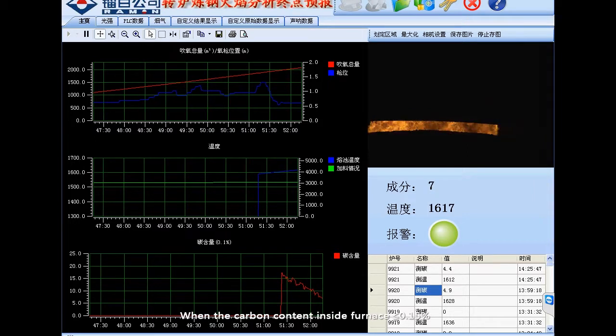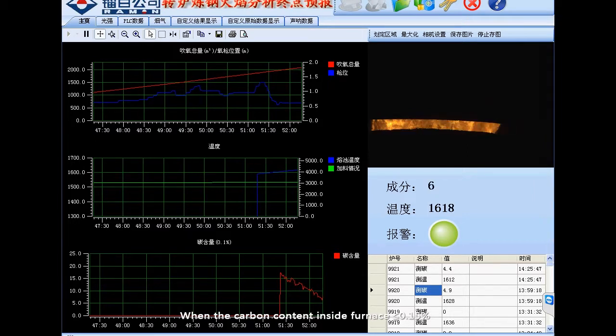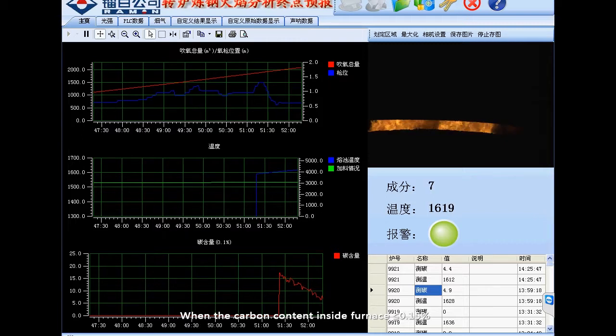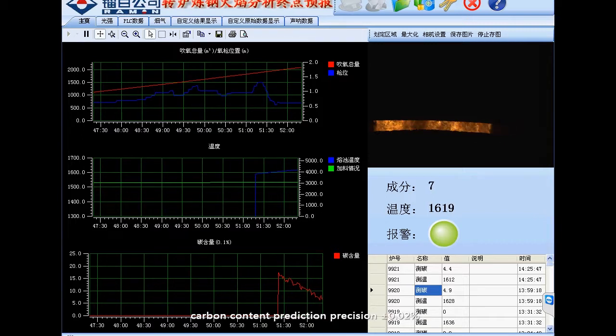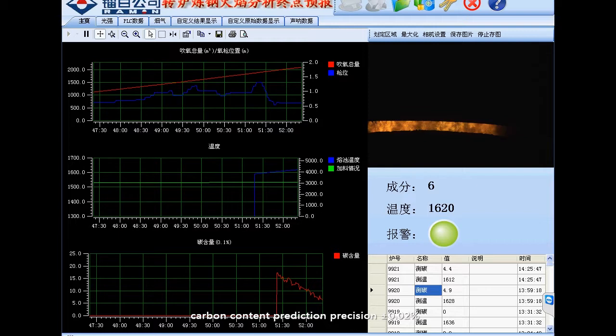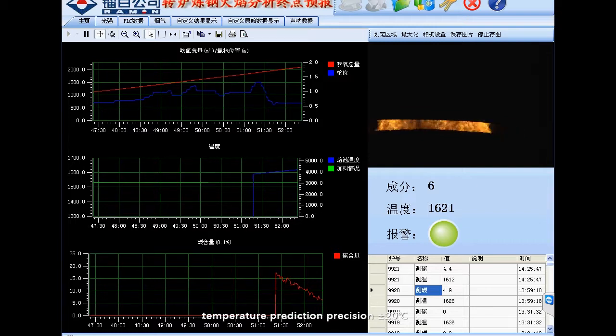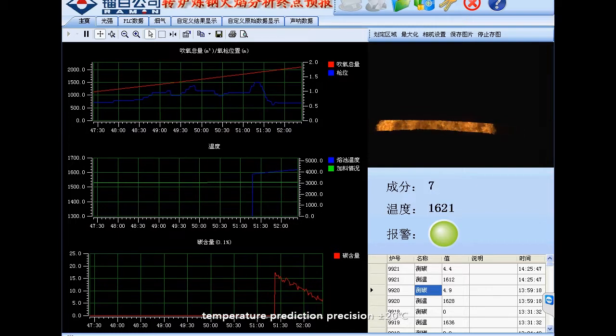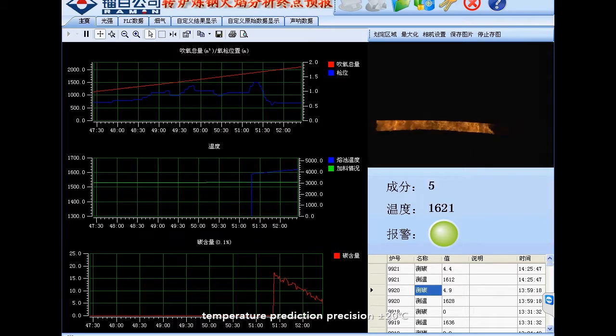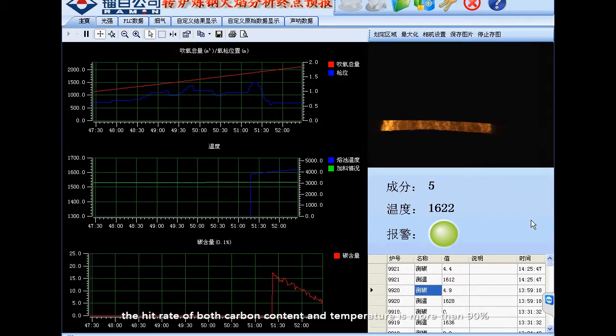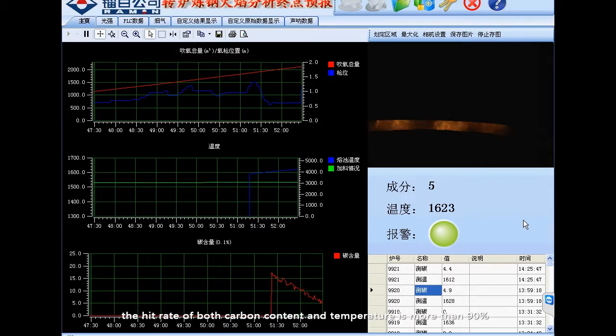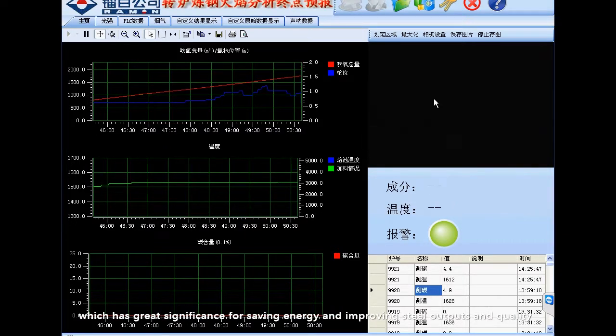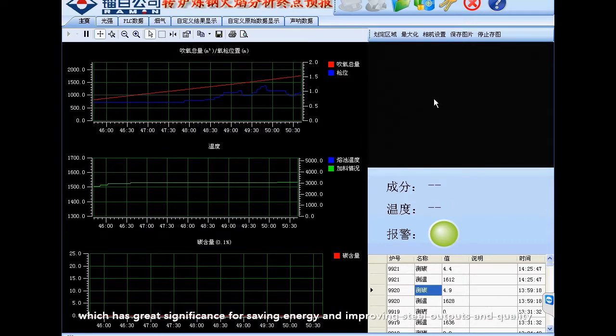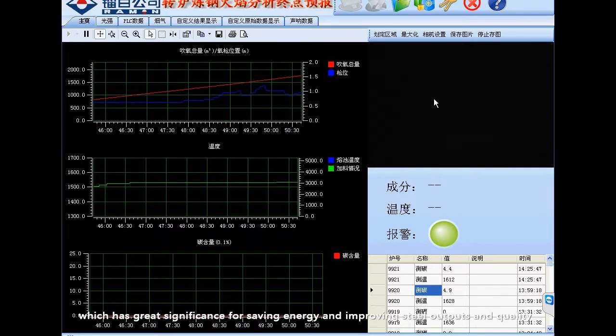When the carbon content inside the furnace is less than or equal to 0.15%, carbon content prediction precision plus minus 0.02%, temperature prediction precision plus minus 20 degrees Celsius. The hit rate of both carbon content and temperature is more than 90%, which has great significance for saving energy and improving steel outputs and quality.